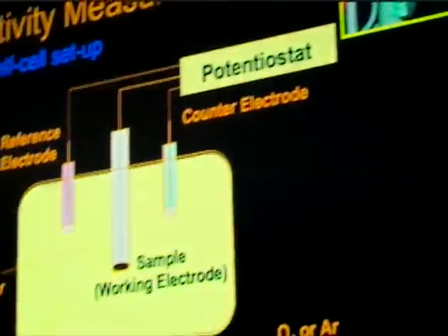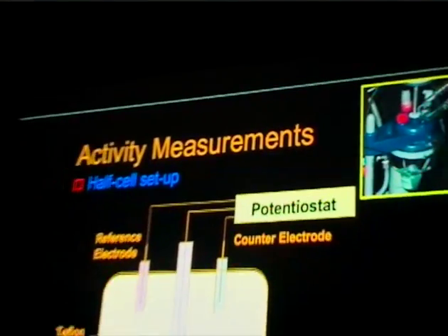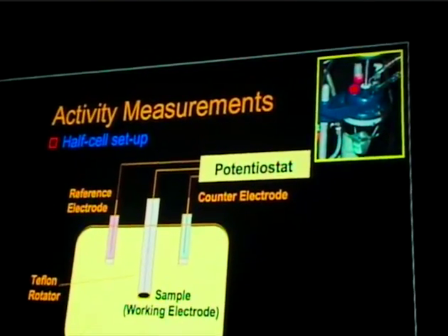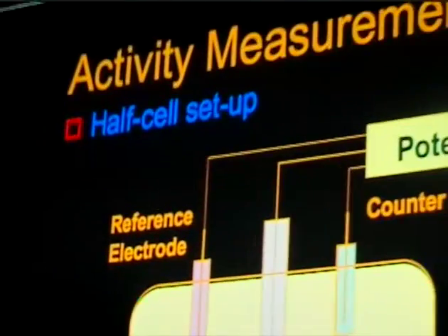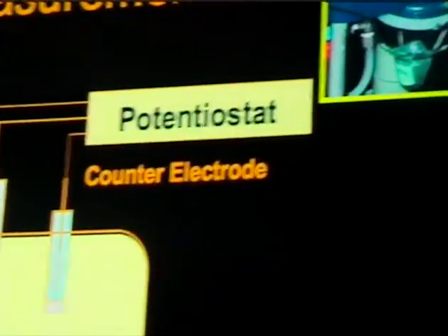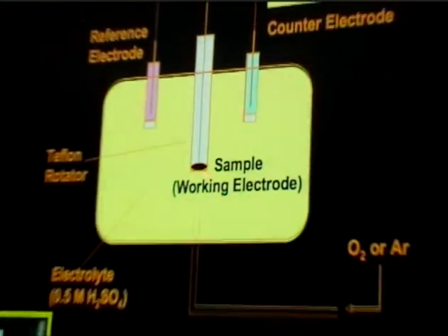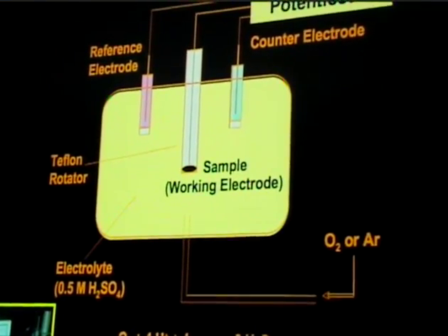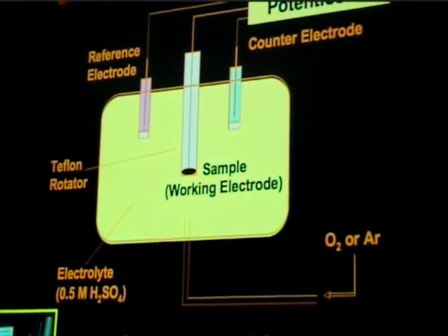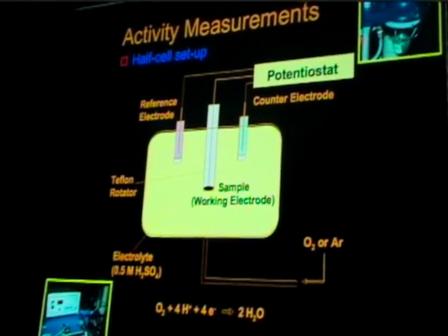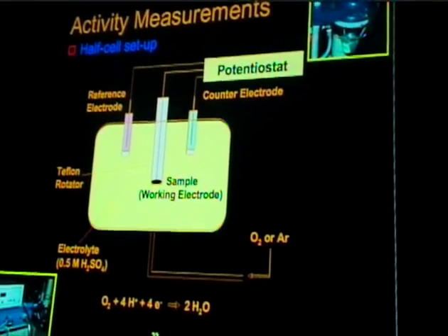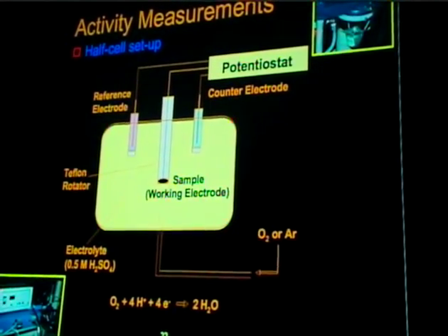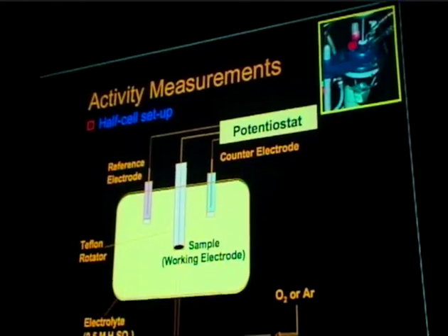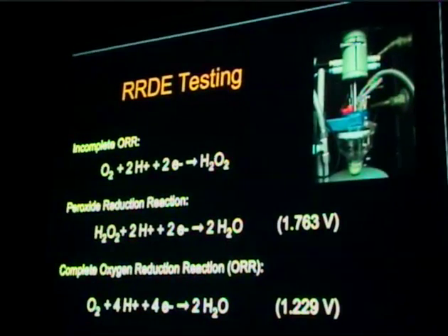And these are relatively easy experiments compared to putting together a membrane electrode assembly each time you want to test a catalyst. We have the reference electrode, a counter electrode, and here's the working electrode at the tip of which we place the catalyst that we want to test. And the electrolyte in this case is an acidic electrolyte mimicking the behavior of Nafion, which is the polymeric electrolyte that is used in PEM fuel cells.